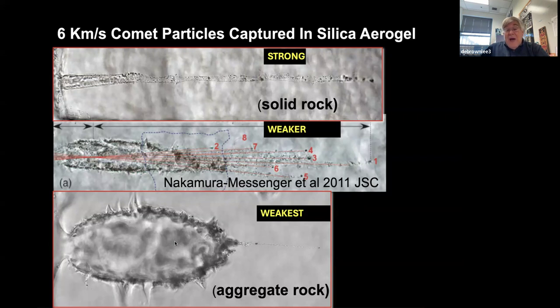This is an interesting track. The little dot on the far right is a sulfide. The little black dot between the sulfide and the main bulb is a calcium aluminum inclusion. A little bit to the left of that, at the bottom of the bulb, is a presolar grain, a silicon carbide grain.